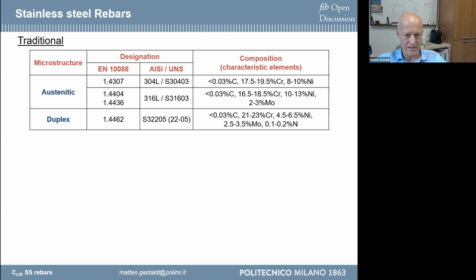I don't want to go into detail, but the traditional stainless steels that were used in construction, in reinforced concrete structures, are generally of two types: austenitic stainless steel and duplex stainless steel. For austenitic stainless steel, which is related to the structure of the steel, I don't want to go into detail. The most used is 304L, the name used in the American standard. This is a stainless steel that has a very high amount of chromium, around 18%, and an amount of nickel that is around 10%. Another austenitic stainless steel that is commonly used is 316L, which also has an amount of molybdenum that is around 2-3%.